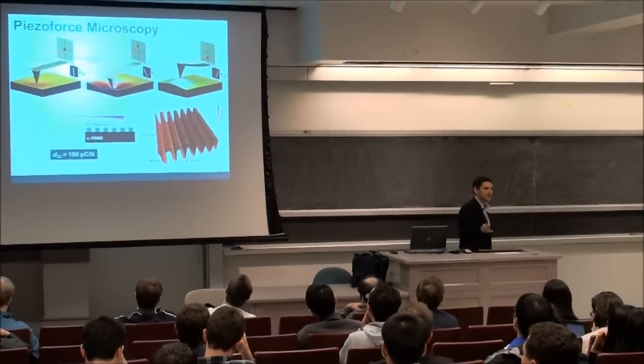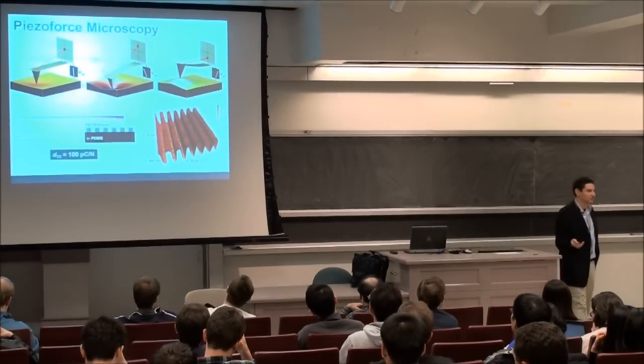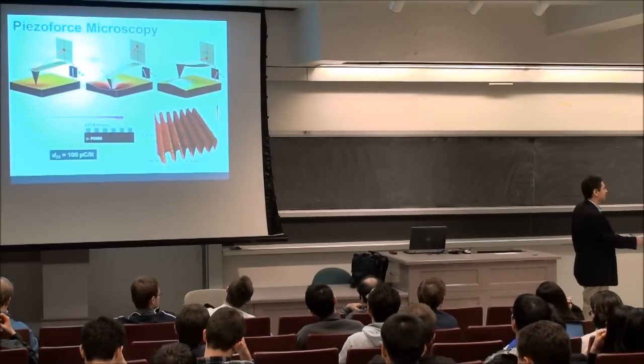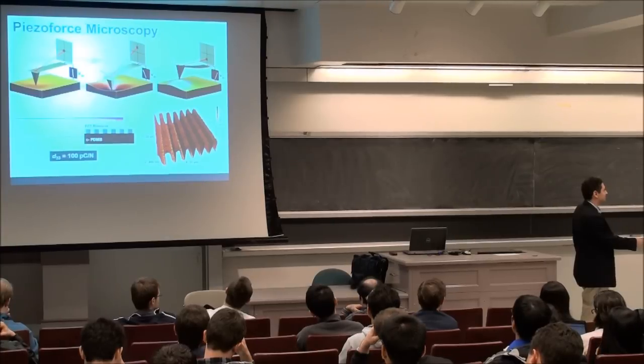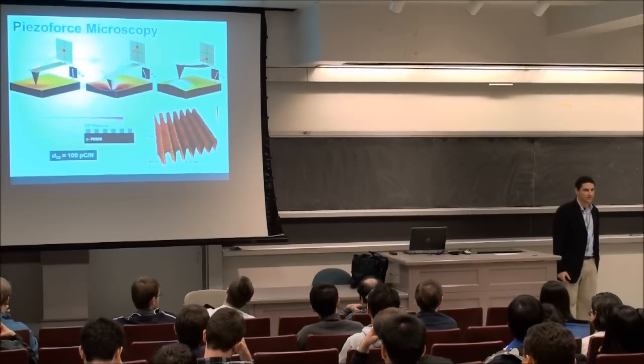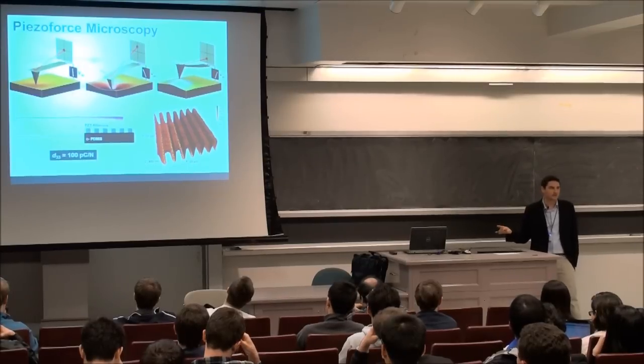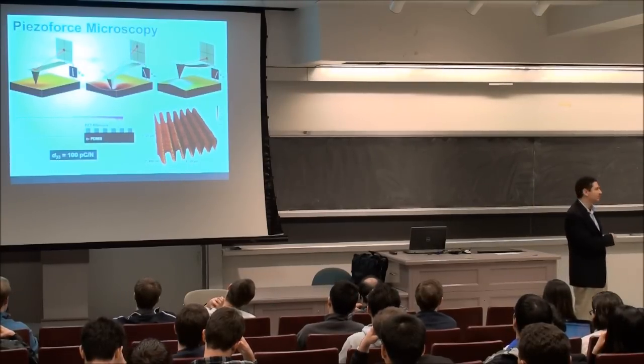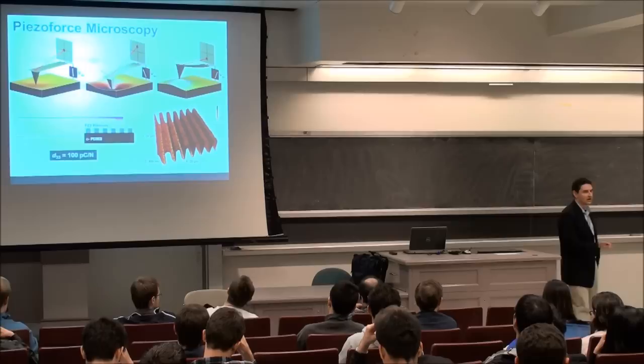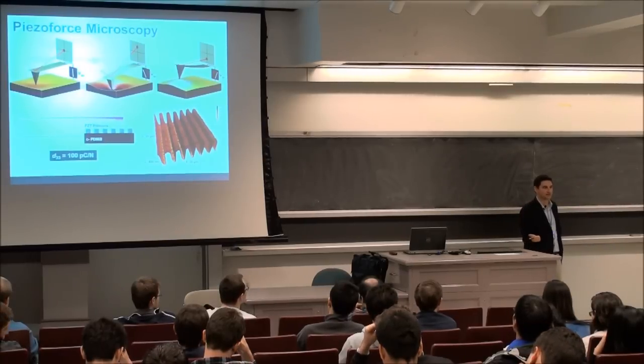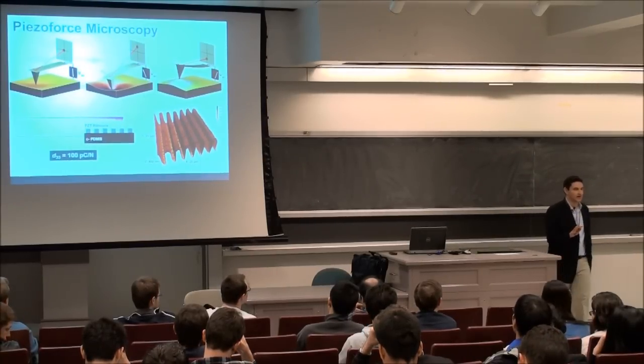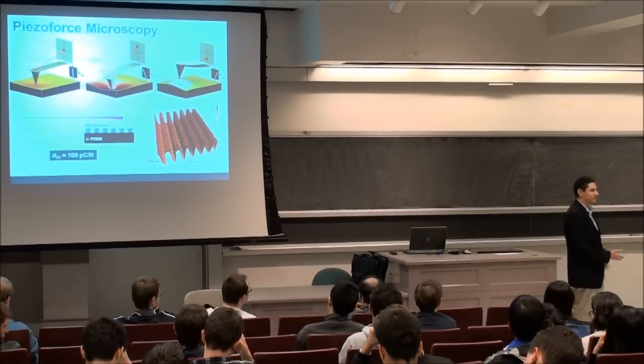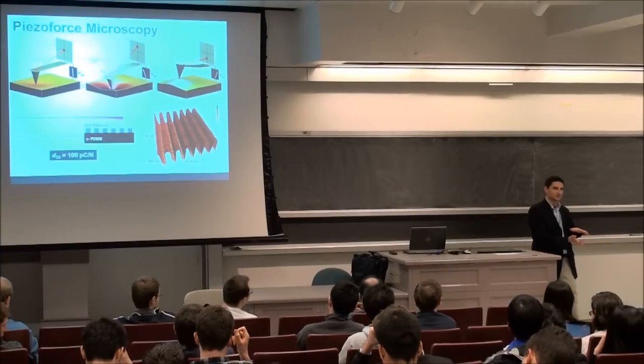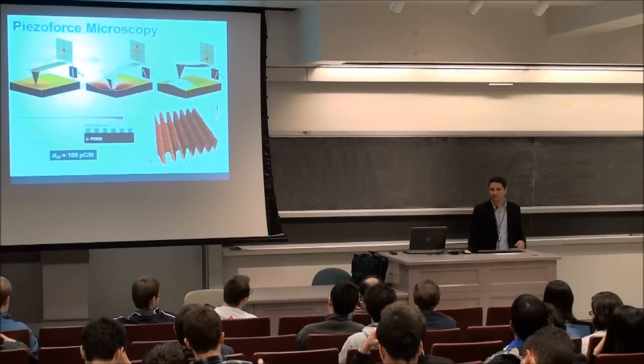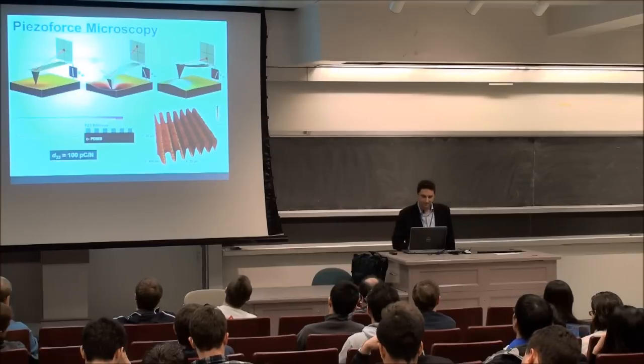So of course this was on PDMS. PDMS is not conducting, so our trick was we actually doped the PDMS with carbon here, and then put the tip there between the PDMS conducting part and then the top of the ribbon there. And we actually got pretty good D values, on the order of 100 here, as you can see. So not the kind of 250 that the bulk PZT is, but there's a reason for that. In thin films of PZT, you're actually dampened slightly by the substrate. In the bulk scale, there's no damping effect here, okay?